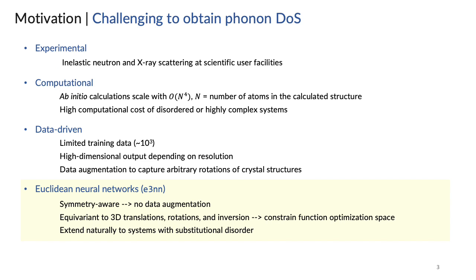Despite its ubiquity in thermal and electronic transport calculations, the phonon density of states is non-trivial to obtain. It can be measured experimentally by inelastic neutron or X-ray scattering, which are limited resources available at scientific user facilities. On the other hand, ab initio calculations scale rapidly with the number of atoms in the structure, incurring a high computational cost for large systems, especially disordered structures.